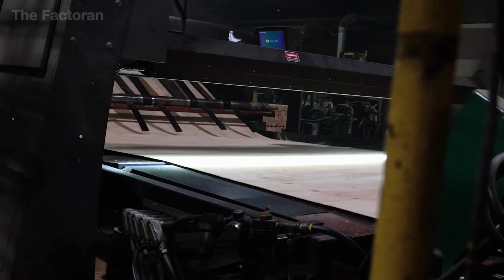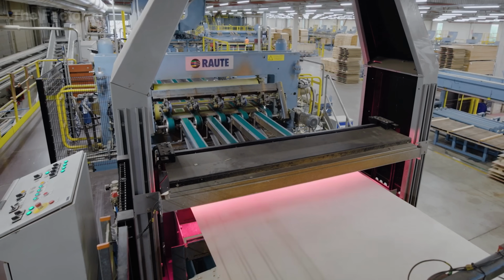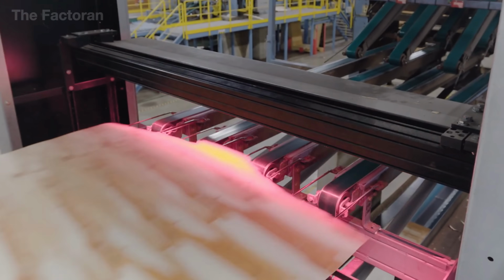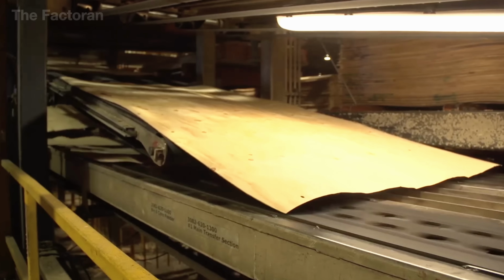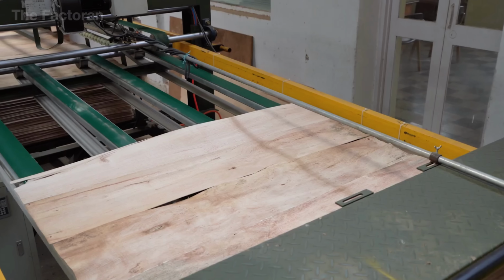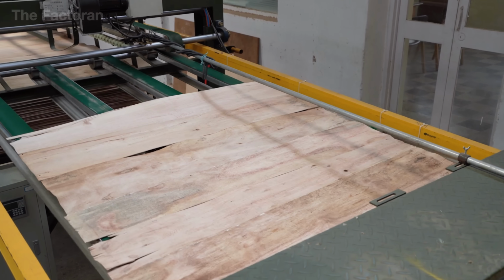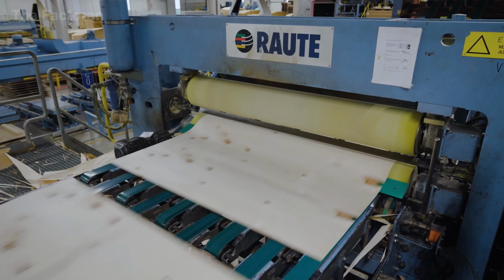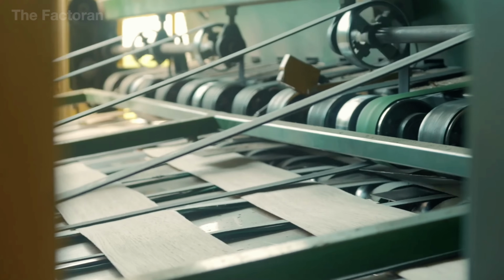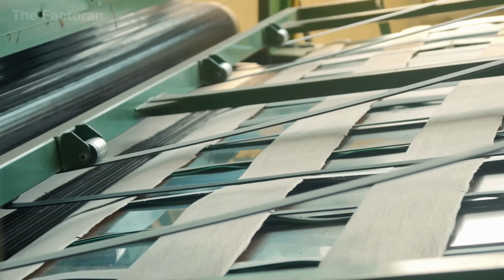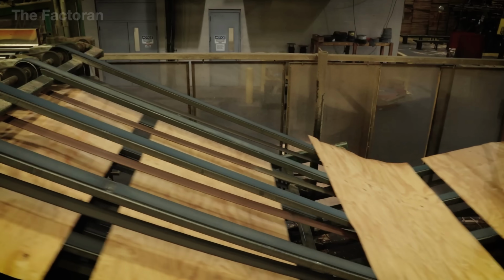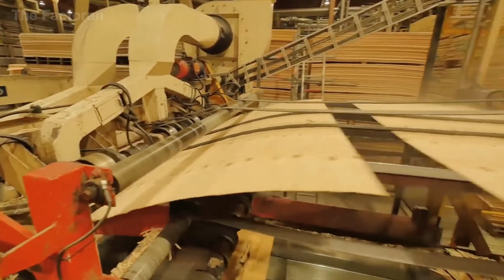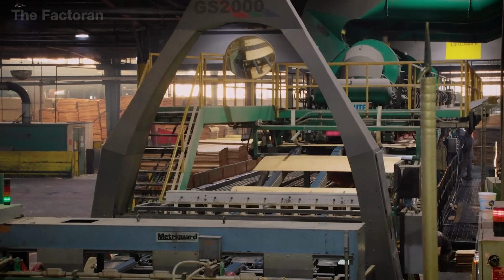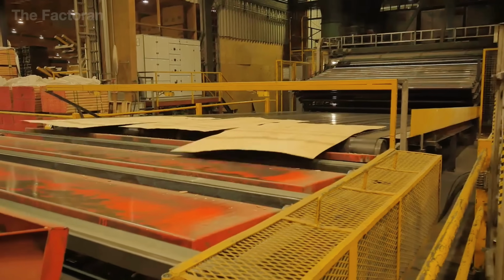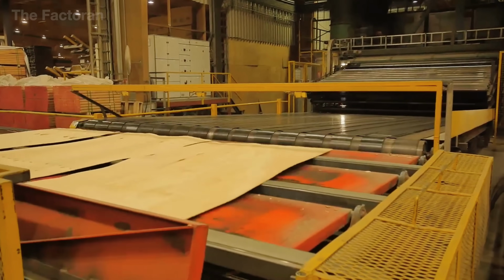This drying process requires a delicate balance. Excessive heat can cause warping or cracks, while insufficient heat fails to reach the necessary dryness. For this reason, sensors continuously monitor temperature and humidity, transmitting data to the control room for instant adjustments. At the end of the chamber, the veneers are cooled naturally in an enclosed environment to prevent thermal shock. The result is a stack of thin, flat, and stable sheets, perfectly conditioned for the next stage of production.